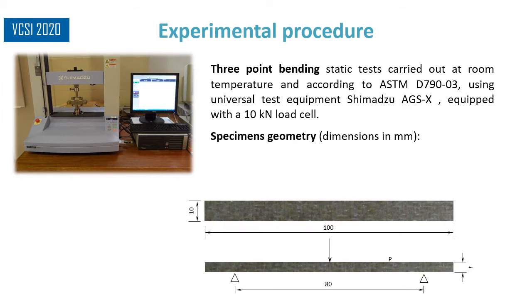Three-point bending static tests were performed using specimens with the geometry shown in the figure and tested with a span chosen according to the thickness and length of the laminate tested, following the recommendations of the standard test. A Shimadzu Universal Testing Machine equipped with a 10 kN load cell was used, and for statistical reasons, at least 5 specimens were tested at room temperature and at a rate of 2 mm per minute.